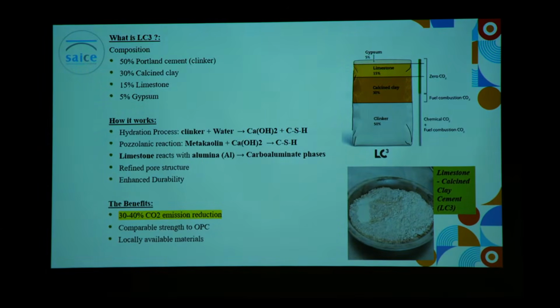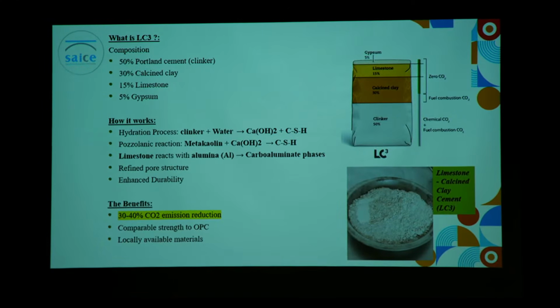The first study material is LC3, limestone calcined clay, an engineered blend containing 50% normal Portland cement, along with calcined clay, limestone and gypsum. It works by starting with hydration, where the clinker content from the Portland cement reacts with water, forming Portlandite, supported by the cementing phase, calcium silicate hydrates. The Portlandite then reacts with the metakaolin introduced by the calcined clay, creating secondary cementing phases, additional bonds within the concrete mixture. Finally, the limestone reacts with the alumina to form carboaluminate phases, the compounds responsible for refining the pore structure within our concrete mixtures.